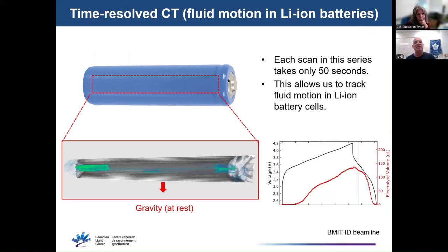Synchrotron CT is very fast, so you can even perform time-resolved studies. This is an example illustrating changes in the liquid electrolyte of a battery. As you increase the voltage in the battery during cycling, the battery electrodes expand, and this causes motion in the electrolyte. Each individual CT scan making up this movie takes less than a minute to collect. And you can study other types of time-dependent behavior as well, as long as they occur slowly enough that you can actually capture them sufficiently.